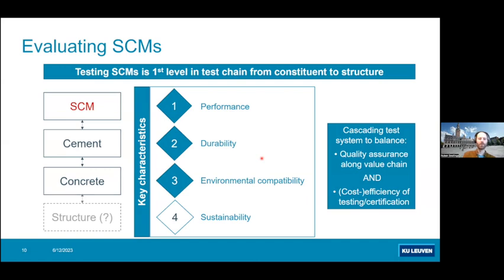Reactivity testing of an SCM is obviously only a first step in a series of performance-based tests. But screening is already very interesting to optimize processes, but also to eliminate off-spec materials or to focus on materials that are of most interest for cement and concrete producers later on. Obviously, there are other key characteristics, durability and environmental compatibility, that need to be tested other than reactivity. But reactivity is often seen as closely linked to performance and durability, so a good indicator, at least, of what an SCM could do in a cement or in a blended cement.